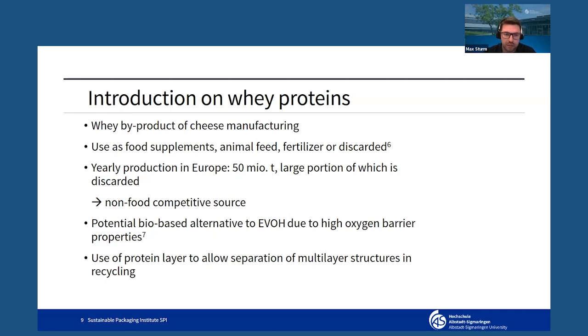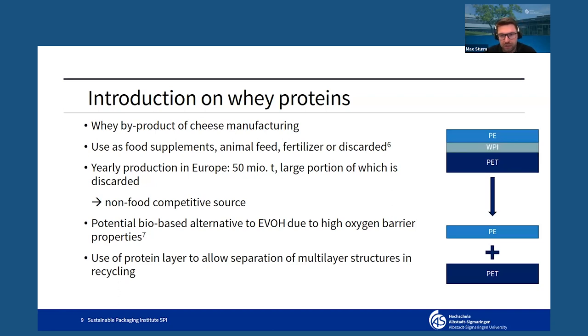And its potential to be used here has been found by multiple studies so far. For example, due to its high oxygen barrier properties, it's a potential bio-based alternative to EVOH, which is currently the most prevalent oxygen barrier coating that's being used. And additionally, it has also the benefit of being enzymatically removable. So for example, looking at this multilayer structure of polyethylene, WPI, which is short for whey protein isolate and forms the basis for our coating solutions, and polyethylene terephthalate, this can be separated by an enzymatic bath in the recycling process. So the two polymer films can be recovered separately and can be used again in a second life application.